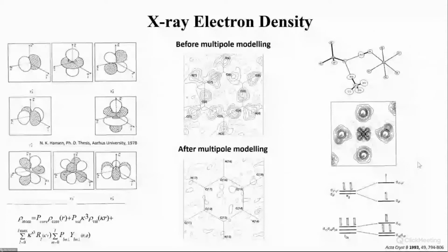Now, I will start this with my very first study, 50 years ago, this study of copper Tutton salt, which is a copper ion with 6 waters around it, then an ammonium and a sulfate. And I spent a couple of months measuring these point detector data at 9 Kelvin with my supervisor, Finn Larsen. And what you could see is this Jahn-Teller distorted copper site. And you could see the chemical bonding here, that the electron distribution has a hole because of the Jahn-Teller distortion in this x squared minus y squared. It was beautifully seen here. And of course, this started my career in electron densities.